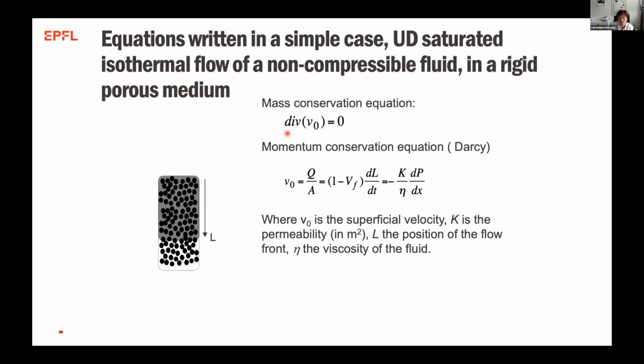In that case, the mass conservation equation is written as in a normal pipe flow: the divergence of the superficial velocity is equal to 0. Then you have the famous Darcy's law, a momentum conservation equation, which tells you that the superficial velocity, which is the flow rate divided by the area of fabric that you go through, is equal to (1 minus VF), where VF is the volume fraction of fibers, times the flow front movement dL over dt. And it's equal to minus K over eta times dP over dx, where K is the permeability of the porous medium, eta is the viscosity of the fluid, and dP over dx is the pressure gradient. Since the fluid is non-compressible and the divergence of velocity is equal to 0, taking d over dx of this tells you that the second derivative of the pressure with respect to x is equal to 0, which means dP over dx is a constant. So we have a constant pressure gradient.